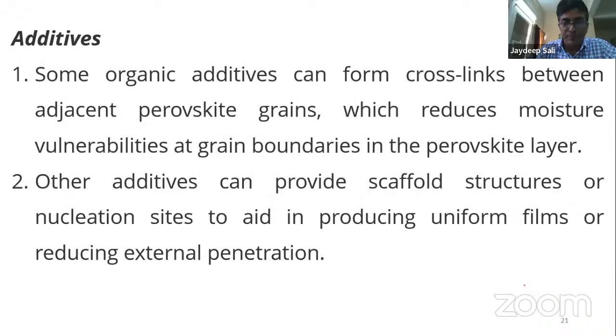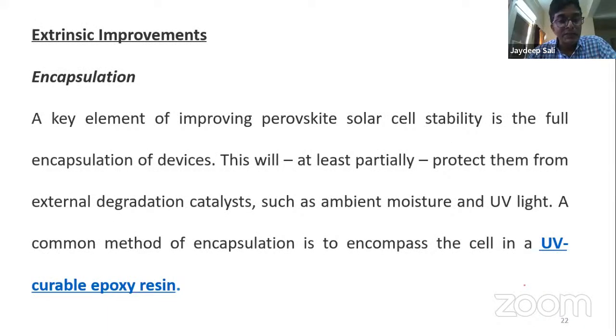So formation of the grains during the perovskite film formation can cause its degradation. We can use some organic additives into it, which can reduce the moisture vulnerabilities at the grain boundary. It can also prevent the path for the moisture to penetrate into the perovskite film, because as we have seen, it is filling up the grain boundaries. Then the additives can also provide some nucleation sites, which can improve the crystalline structure of the perovskite and reduce the penetration probabilities. Okay, so when we prepare thin films of the perovskites as a photoactive layer, we can add certain additives into it, and it can lead to stable perovskite thin films. Okay, this is one way.